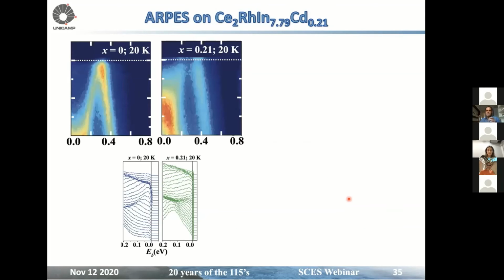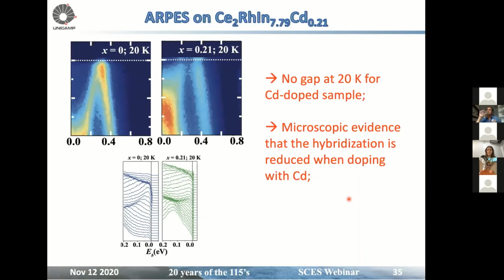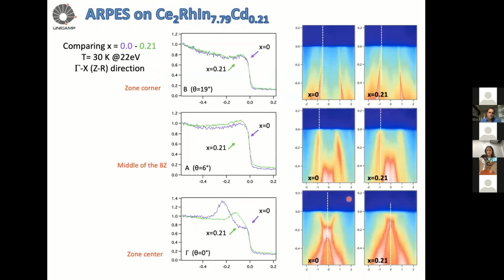So, if we dope with cadmium, we see no gap at all. It's another microscopic evidence that hybridization is being reduced when we dope with cadmium. I'm just showing you very fast that if we go to the other places of the Brillouin zone, at the corner we see no difference. At the middle of the Brillouin zone, no difference between doped and undoped sample. All the difference is around the zone center. It's shifted by about 100 meV when we dope the sample.